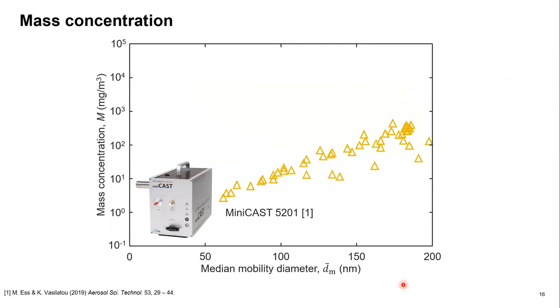As I mentioned before, one drawback of generators such as the miniCAST and from real engines is that we get relatively low mass concentrations, which make it difficult to perform certain offline characterizations. Here we see the data of the mass concentration on a log scale versus the median mobility diameter from a miniCAST. As you can see, when we go to the small sizes that are the most relevant for aircraft engines, the mass concentration decreases by nearly two orders of magnitude compared to the particles when they have several hundred nanometers of mobility diameter.